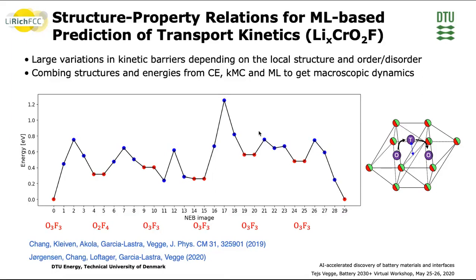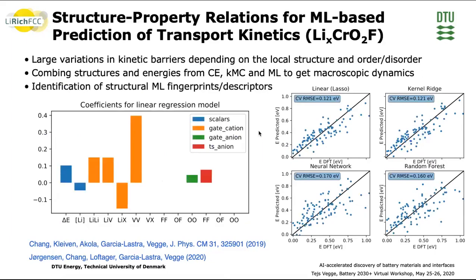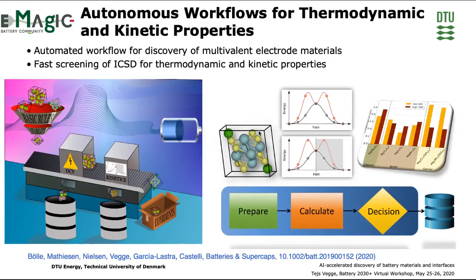So understanding and predicting how the structure and the composition changes the kinetics is essential if we want to predict macroscopic transport properties. By using machine learning techniques, we can then identify certain fingerprints or descriptors like changes in energy, concentration of lithium, combinations of cation and anions that dictate the transport kinetics that allows us to describe and predict the macroscopic transport properties. Another essential aspect in Big Map is really establishing autonomous workflows. So workflows that allow us, without human intervention, to analyze, predict, and select suitable materials.